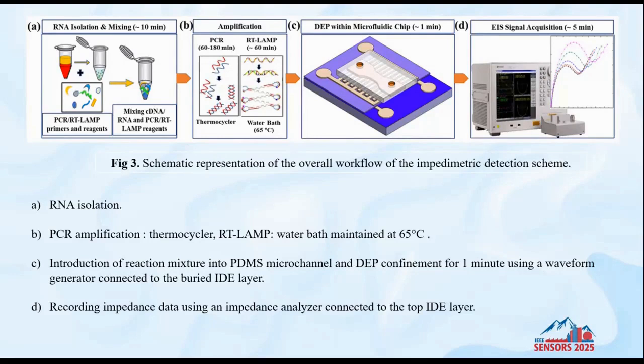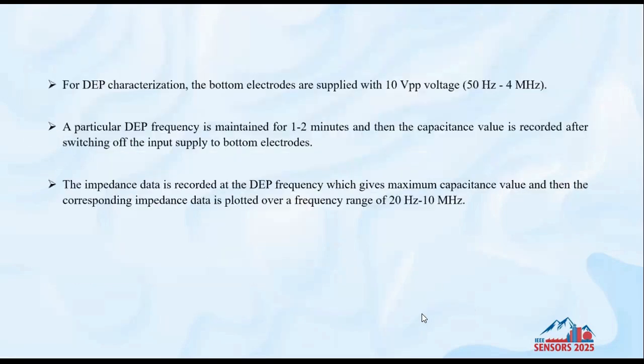A waveform generator is connected to the buried IDE layer for DEP confinement, and that happens for 1 minute near the electrode surface at an optimal frequency of 500 Hz and 50 kHz for unlabeled and gold label primers, respectively. Subsequently, the impedance data are recorded using an impedance analyzer connected to the top layer IDE, as can be seen in figure 2D. So for DEP characterization, the bottom electrodes are supplied with 10-volt peak-to-peak voltage at a frequency range of 50 Hz to 4 megahertz. The parallel capacitance value, which